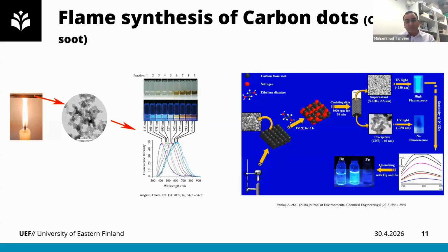The other option is that candle soot can be doped with nitrogen or some other heteroatoms so that the properties of the carbon dots can be changed, and then their application can be tuned accordingly. In this study, they have doped carbon dots with nitrogen, modified the surface chemistry, and then used it as a detection material for water treatment systems. They can detect heavy metals like mercury and iron. So it has application in these areas.